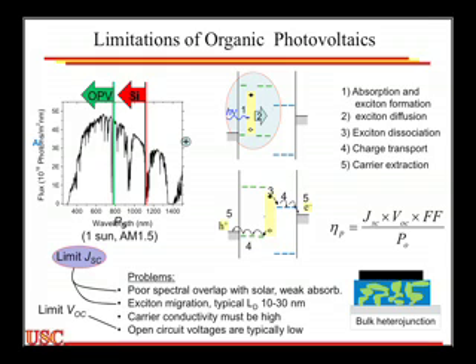That's a huge limitation. And so there's a lot of people, my lab and elsewhere, that are pushing the absorption manifold as far out as we can, because that gray area is what we want to collect. There's another problem that comes from this as well, and that is that because the exciton is so strongly bound, it doesn't migrate very well. That is, there's a relatively big reorganization energy for the migration of that exciton. And so typical exciton migration lengths are on the order of between 10 and 30 nanometers.